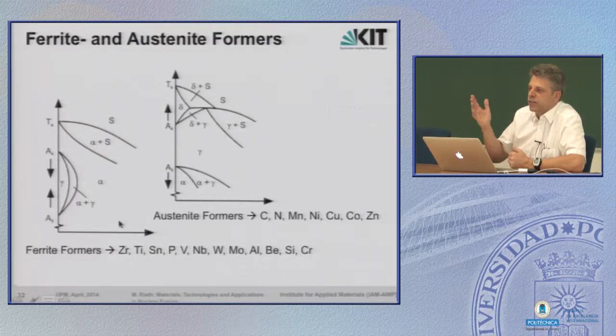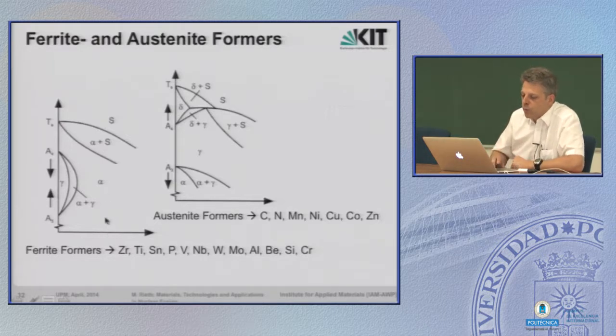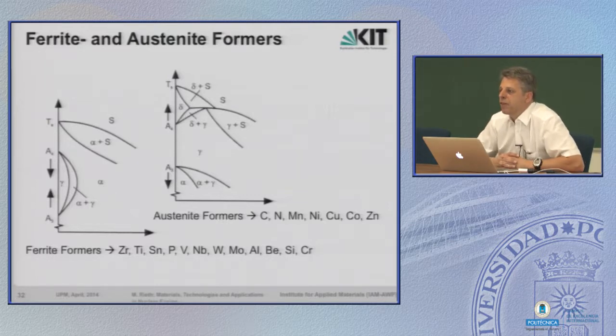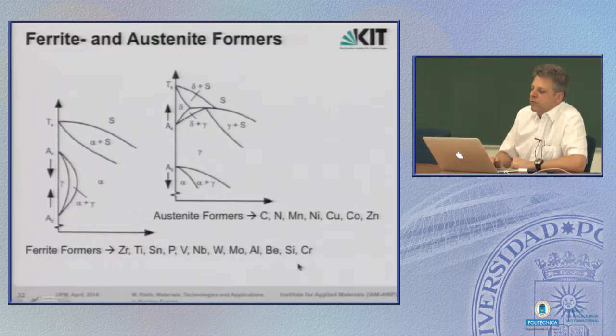For example, if you use steel with 16% chromium, you would be along this line here, and what you have is a steel without phase transition. It always has a ferrite phase, nothing else. If you reduce the amount of chromium, the border here is at 12%, which is an important one. If you have a steel with less than 12% chromium, then you end up in this phase field, and then you still have phase transformation. This would result with 9% chromium in